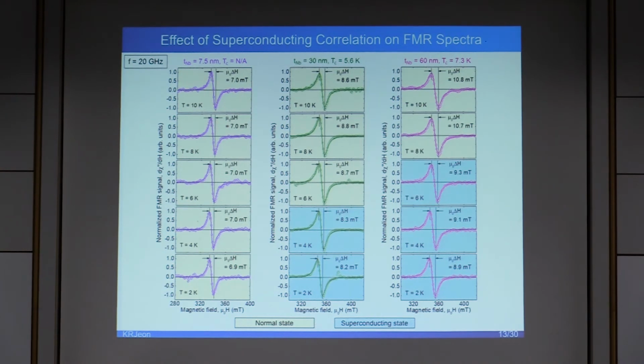When the niobium thickness is 7.5 nanometer, which is non-superconducting in this range of temperature, the FMR line width varies slightly with the decrease in the temperature. In contrast, for the 30 and 60 nanometer, the FMR line width is suddenly reduced by going through Tc, and the observed sudden reduction is more pronounced in the thicker niobium layer.